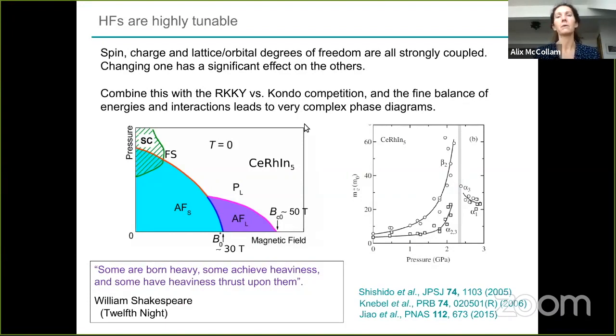about what's going on. And what I will talk about in the rest of the talk are measurements of the de Haas-van Alphen effect, where we have extracted the de Haas-van Alphen frequencies, which give us a measure of the shape of the Fermi surface, and the effective mass, which gives us a measure of the renormalization associated with the f-electron and conduction electron coupling. And in particular, we'll look at how the Fermi surface changes as you go from something like an ordered region to a paramagnetic region.